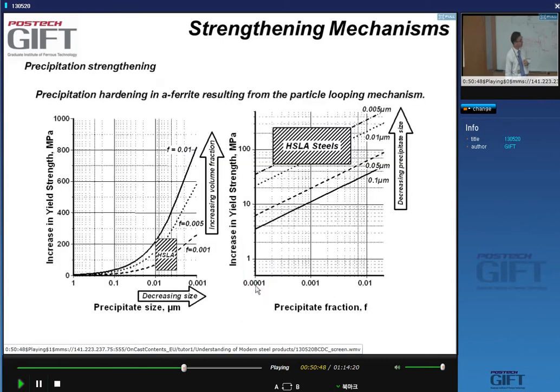And if you apply this equation, for instance, to HSLA steels, this is what you get. So this is the increase in the yield strength as a function of the size, and the size decreases from left to right. So you get a very strong increase in the strength. And as you increase the volume fraction of the particles, you also get an increase in strength.